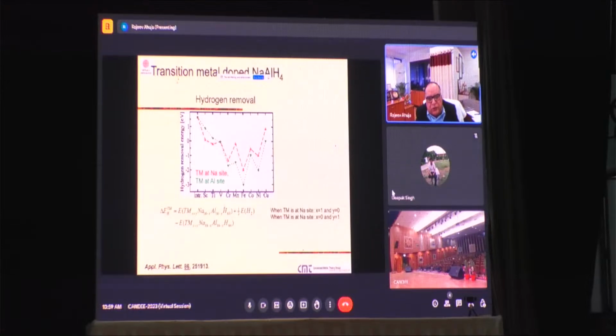We took only the 3D metal catalysts because we don't want to use 4D and 5D material because they are much heavier. So my weight percent of hydrogen will go down. So what we did, we plot the hydrogen removal energy on the y-axis versus the different catalysts, and you can see that hydrogen removal energy is lowest for iron if you compare with the titanium trichloride. So it's almost by a factor of 3. So if I use iron trichloride as the catalyst, I can further reduce the temperature by a factor of 3 compared to the titanium trichloride.